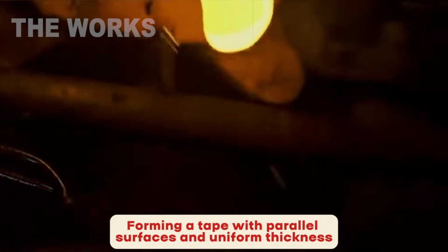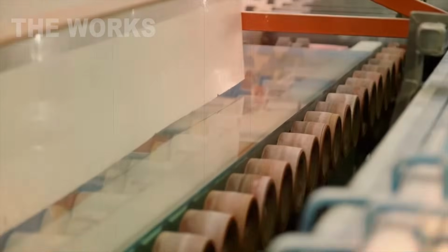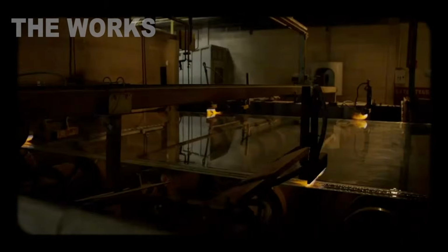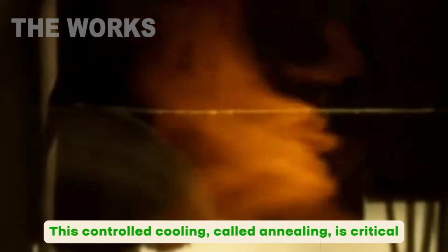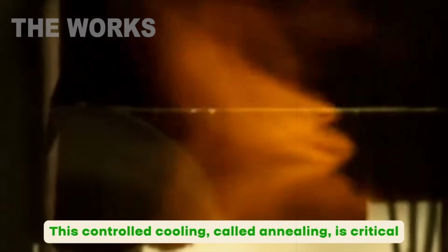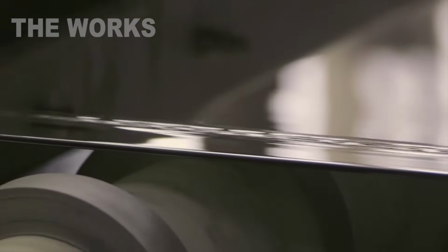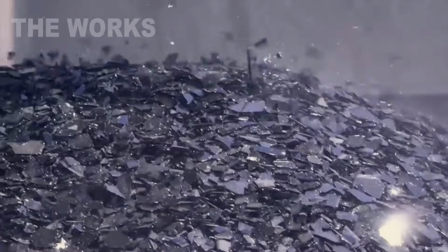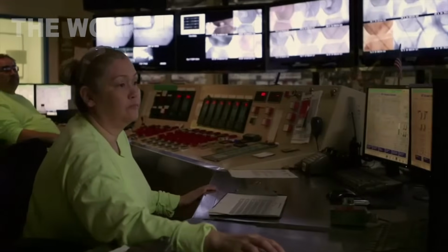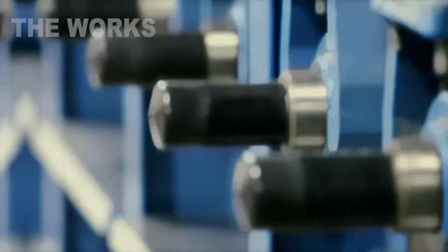Watch as the glass ribbon advances through the tin bath. Temperature is carefully controlled, gradually cooling as the glass moves forward. This controlled cooling, called annealing, is critical. It relieves internal stresses that would otherwise cause the glass to crack or shatter during cutting or installation. As the glass exits the tin bath, it's cool enough to be supported by rollers, entering what's called a lehr, a long cooling tunnel where temperature continues to drop under precise control.